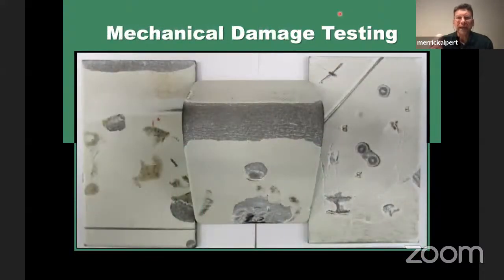Now, the data I'm showing you now, these slides are from Chevron Corporation. I can show you these because Chevron went public with this in 2018 at the EUROCORR conference in Krakow, Poland. I was sitting in the audience watching. We were not part of this testing, and we were only shown this after Chevron completed the testing. They were trying to simulate mechanical damage just to see how tough and robust the Eon coating was with a passivation layer. So they started with 3 flat panels. They bent this panel in half.